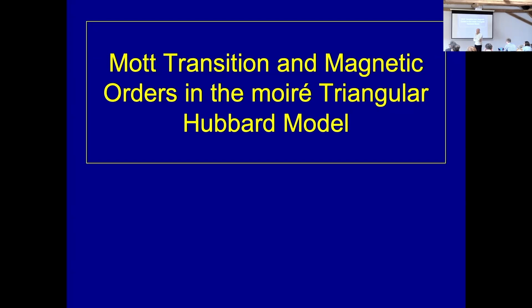Well, the answer is simple. Now, reality may be quite different. If really there is quantum critical, you see, I'm an agnostic on this. I look at this with amazement, and I still need to be convinced. If you actually have genuine quantum critical scaling in the system, we know what happens. You open Sachdev's book, right? And you will read that most of the time you have h bar omega over kT scaling. And in cuprates, for example, there are actually a few recent papers on arXiv, in the past weeks, about this. There is beautiful omega over T scaling in the quantum critical regime or strange metal regime of cuprates. So one can take inspiration of this and see if you're optical, we can discuss this, because I scaled cuprate data myself recently. So you should expect h bar omega over kT scaling. Does that apply even to the DMFT solution for optics? I don't know if this has been looked at in this regime, actually. It's a good question.